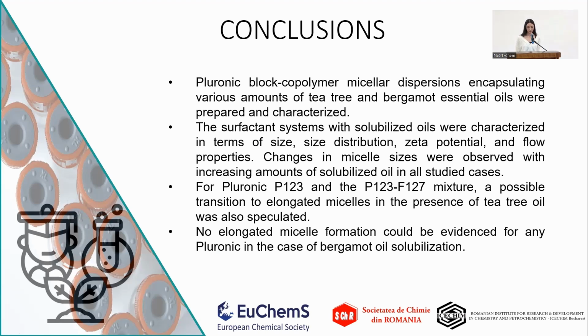Changes in micelle sizes were observed with increasing amounts of solubilized oil in all studied cases. For pluronic P123 and the P123F127 mixture, a possible transition to elongated micelles in the presence of tea tree oil was also speculated. Unfortunately, no elongated micelles formation could be evidenced for any pluronic in the case of bergamot oil solubilization.